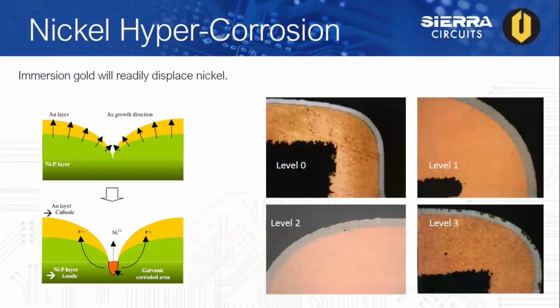As mentioned earlier, for ENIG, the immersion gold will displace the nickel. The nickel gives up electrons if there is an accepting species, which for ENIG involves the gold. Shown in the picture on the top left, the deep crevice lacks gold, which allows positively charged hydrogen ions to pick up the electrons and cause the nickel to corrode without gold deposition. This ultimately leads to a deeper gap, shown on the bottom left.